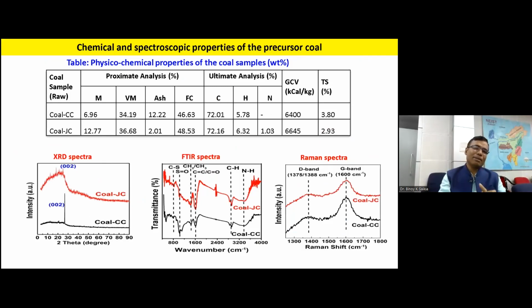So the chemistry of the raw material, if I say, you can say that coal is nothing but a carbonaceous material, it has around 70 to 80% of carbon. Interestingly, they have nitrogen and also sulfur. So those have a very good impact on their fluorescence properties, and because of the functional group, this can also help in getting the different emission. But particularly, we have got now blue and green emission is very prominent in our studies.